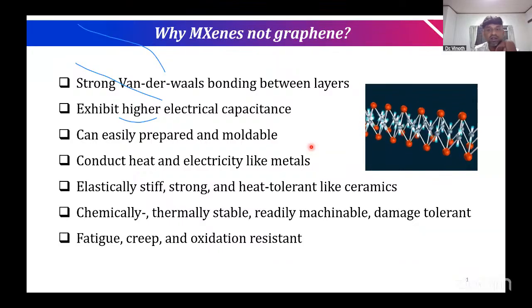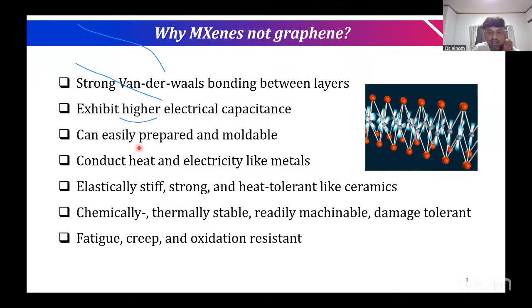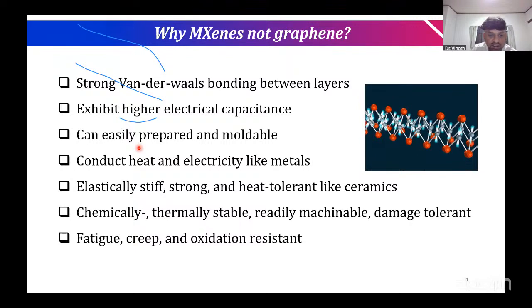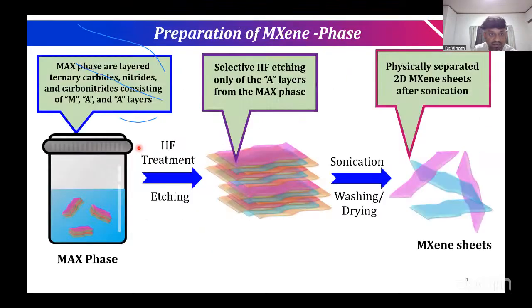Here we can consider why MXenes and not graphene. When compared to graphene, MXene has strong van der Waals bonding between the layers, high electrical capacitance, can be easily prepared and is moldable, and conducts heat and electricity like metals, and is elastically stiff, strong, and heat tolerant like ceramics, chemically and thermally stable, and also cheap, and fatigue, creep, and oxidation resistant. Here is the simple synthesis protocol of MAX phase MXene, with HF etching, which produces single layer and layered MXene. Selective etching produces layered MXene, and single layer MXene sheets are physically separated from the sheet after sonication.